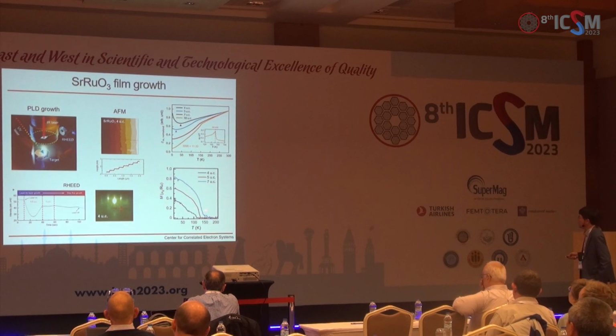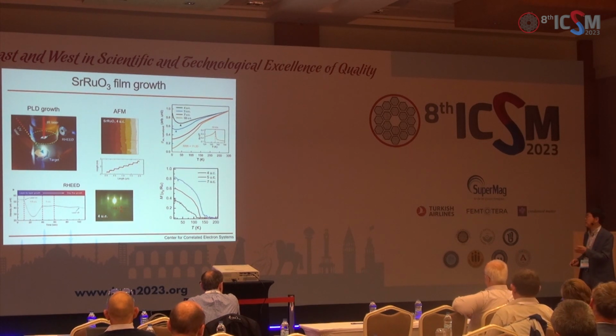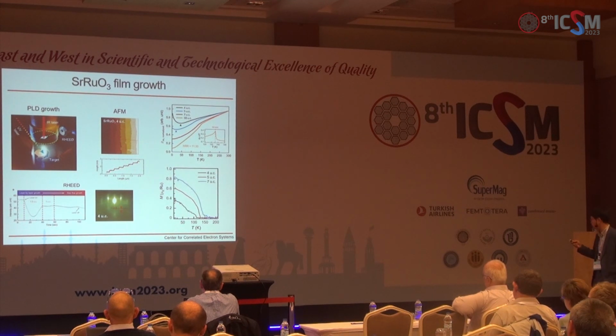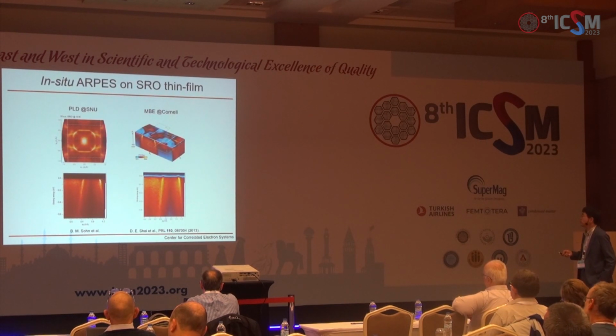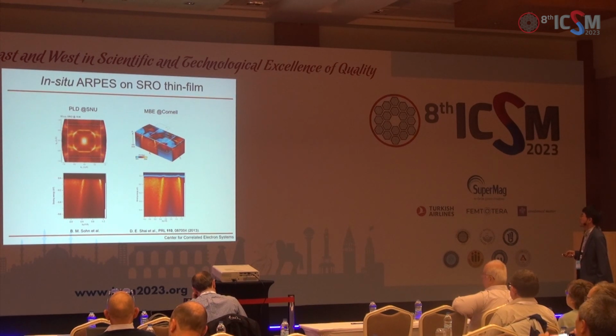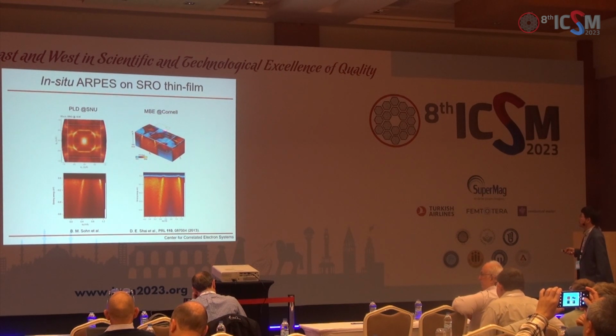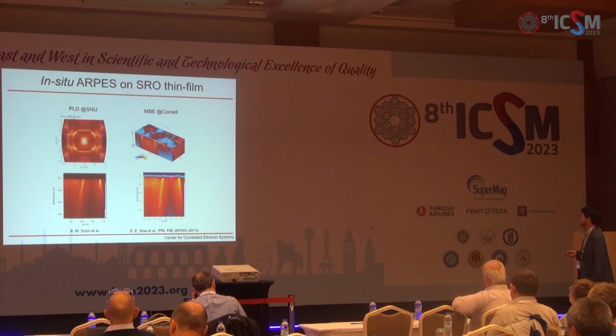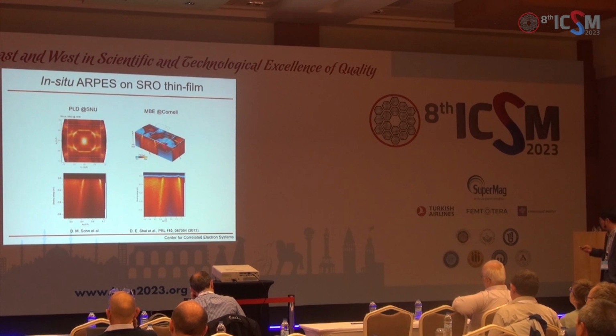Now we measure magnetization for thick films. TC is slightly lower than the bulk value, but at 4 unit cell, it's down to 110 or 120 Kelvin. If we grow less than 4 unit cell, 3 unit cell is sort of ferromagnetic, but below that it becomes paramagnetic. So now here is in situ ARPES. I think this was 4 unit cell, which can be compared with in situ ARPES on a strontium ruthenate thin film from Cornell, grown by oxide MBE. As far as ARPES goes, the quality seems quite similar. So we know that we have a fairly good film here.